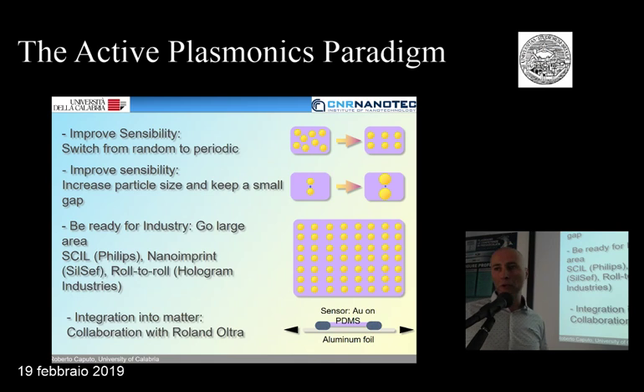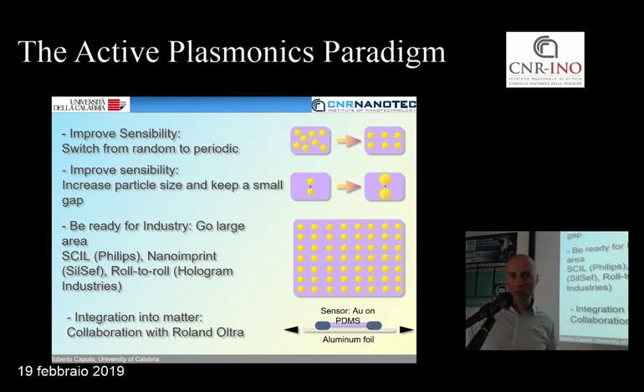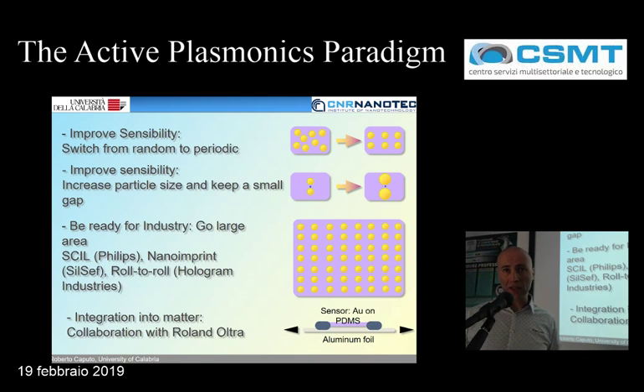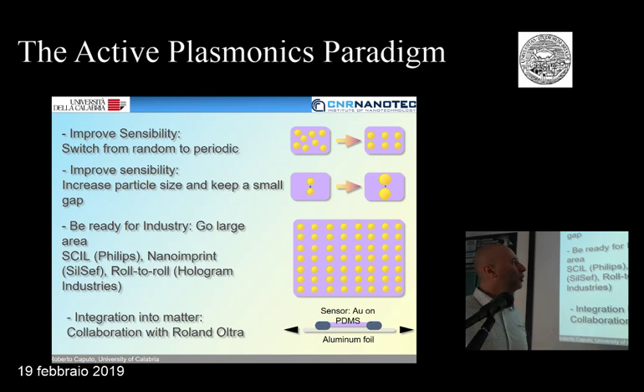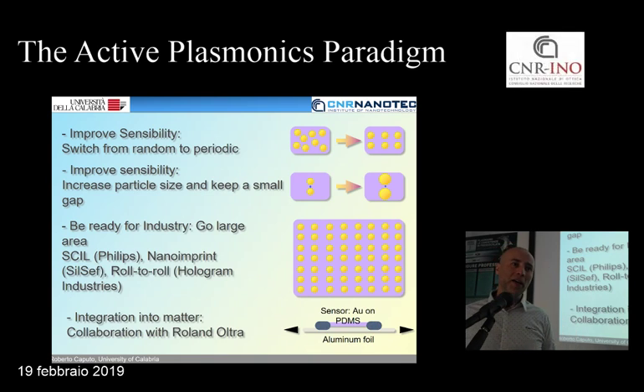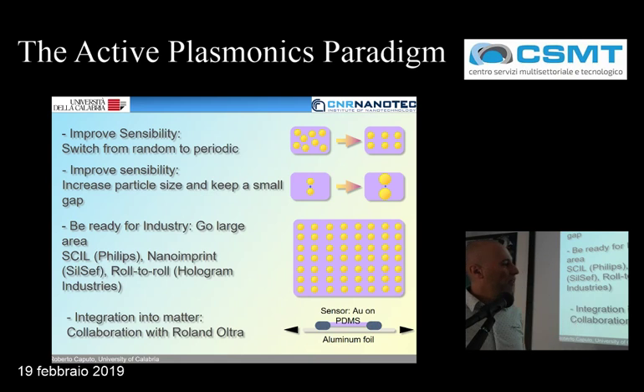Another possibility is to move from a random distribution of particles to an ordered one, where you have more control over what you want to couple, let's say, which particles are going to couple. So in the last period we have been performing some simulations to optimize this kind of response. And of course, for industry needs, you have to maximize the size of these ordered samples. So we are in collaboration with a group in Germany, where they are able to immobilize the particles in an ordered way on the substrate, and we expect very nice results in the following for this kind of activity.